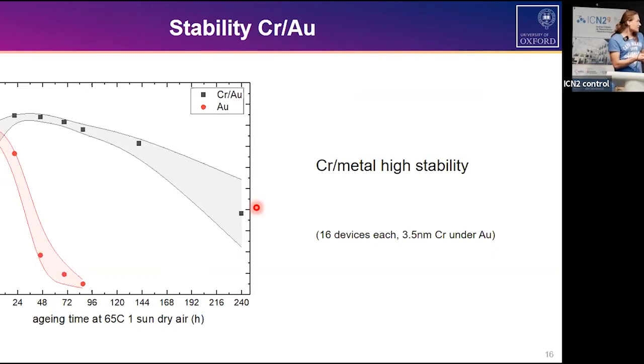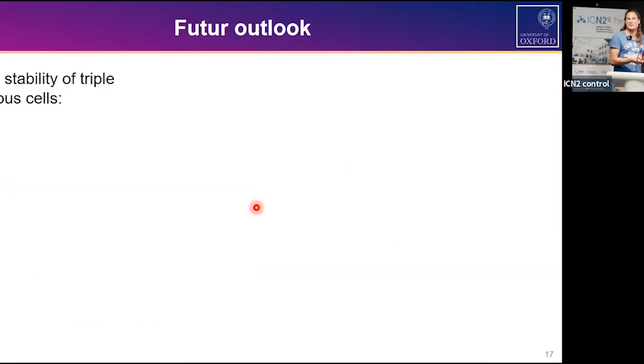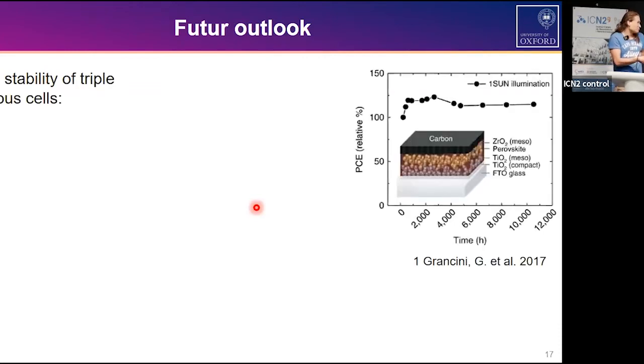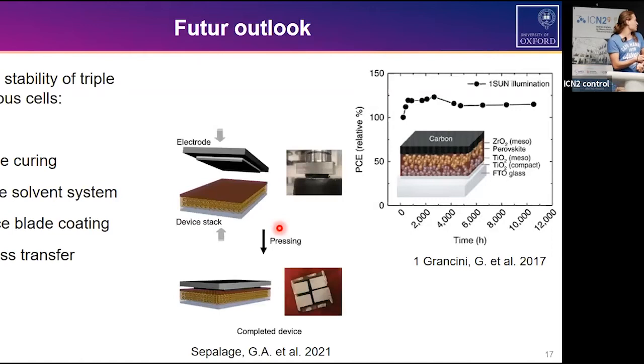So we're aiming, after we achieve the stabilities, for higher stabilities than this firstly introduced, maybe a lot of you know this paper, the 1-year stability, which was on a triple mesoporous architecture, really impressive in 2017. So we want this kind of stability with our efficiencies, or maybe even a bit more efficiency than we got in a planar PIN carbon device. The next things I'm planning to do are to improve the curing and change the solvent system of both the carbon electrode setup and the N-type layer to see what that does to stability.